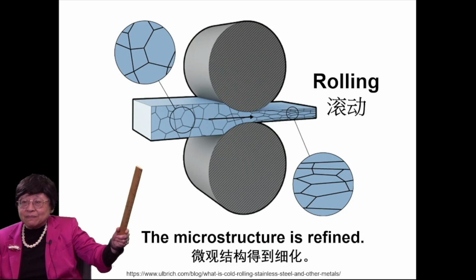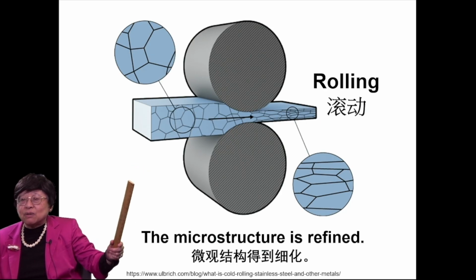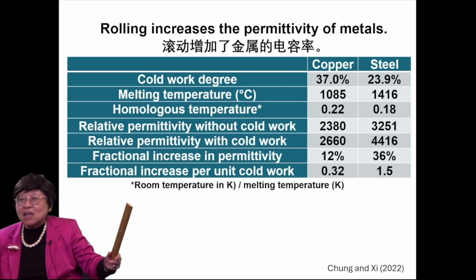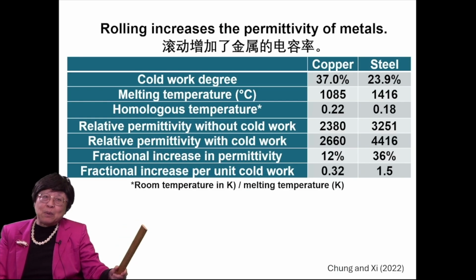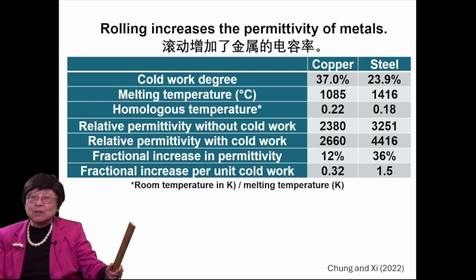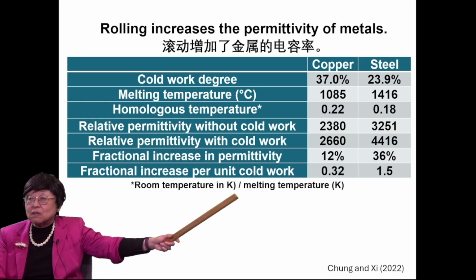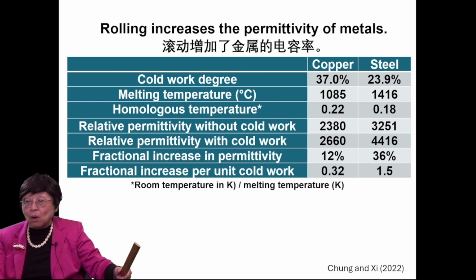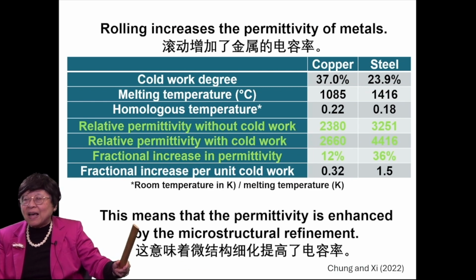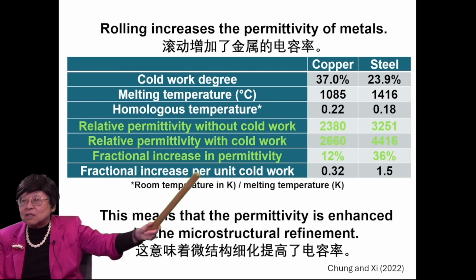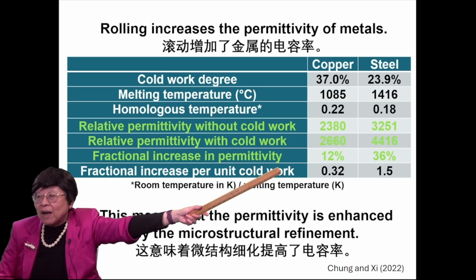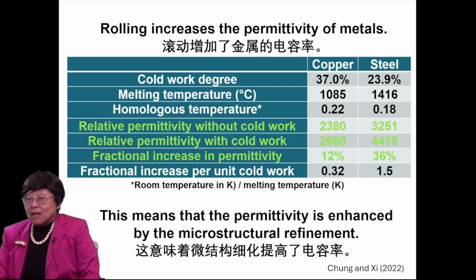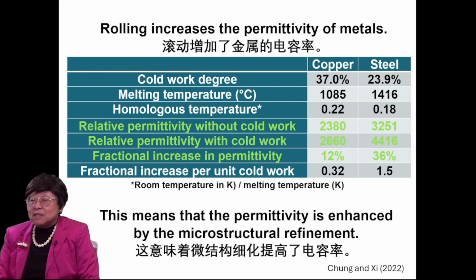Upon rolling, the microstructure is refined. Okay. So carbon cannot be rolled, it's too brittle for that, but metals can be rolled. So we took copper and steel sheets and rolled them, and we find that the rolling causes the permittivity to increase quite a bit. This means that the permittivity is enhanced by the microstructural refinement.